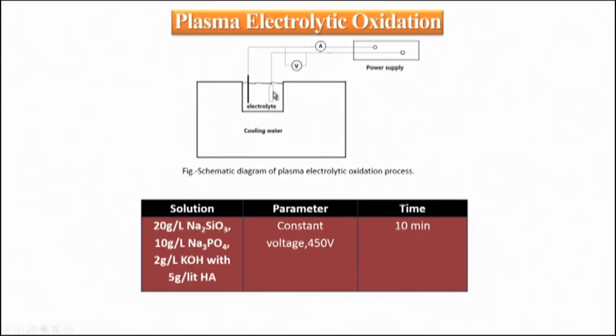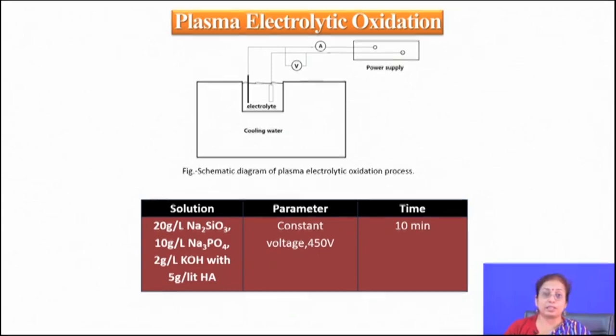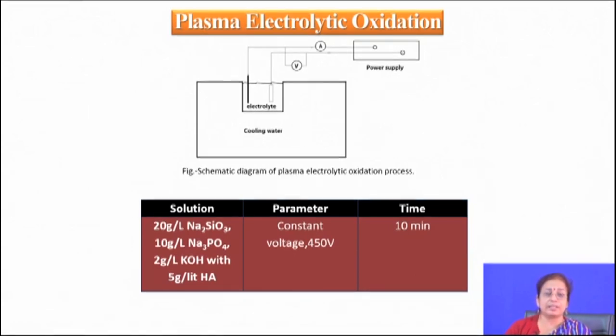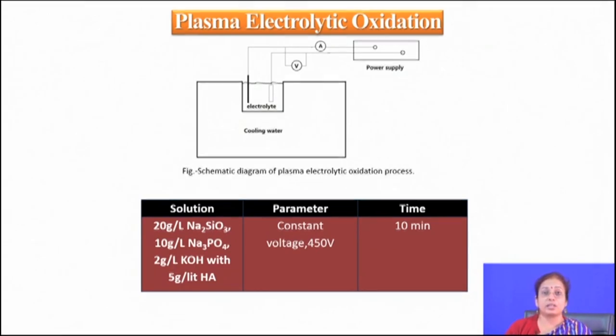In the MAO process setup, the component is taken as the anode and stainless steel or a non-consumable material like graphite can be used as the cathode. A very high voltage power supply unit is attached to the cathode and anode using AC current. During the on-cycle, there is formation of oxide scale, then its breakdown, generation of a high-resistance region, melting of the underlying metal, and transportation to the surface. During the off-cycle, the transported metal solidifies, and then in the next on-cycle it gets oxidized. Each on-time involves an oxidation process and each off-time involves transportation of molten metal, so the process proceeds in a layer-by-layer fashion.